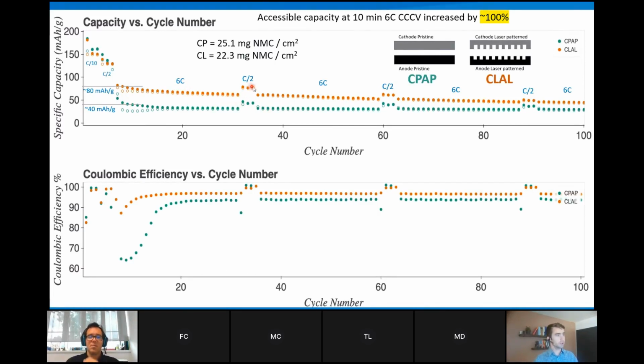So even at the C/2 at 50 and 100 cycles or so, or that looks like about 30, the capacity of the laser ablated channel is higher for C/2, and that's expected, as the non-ablated electrodes incur very severe lithium plating. Now, we still expect that the ablated electrodes will incur lithium plating, that we're still working on quantifying, but you can see the capacity maintained at C/2 is much greater. So we expect the plating here is much more severe than here.